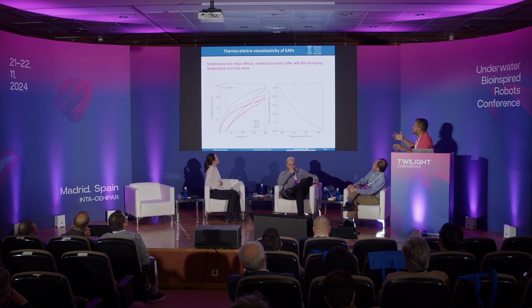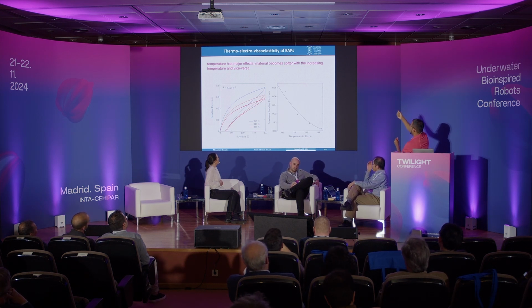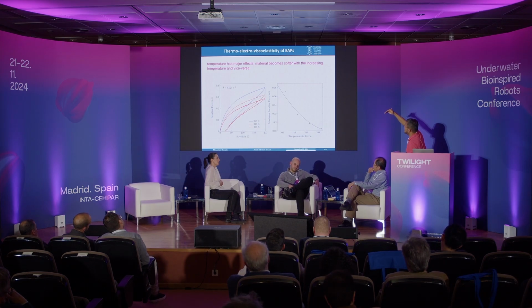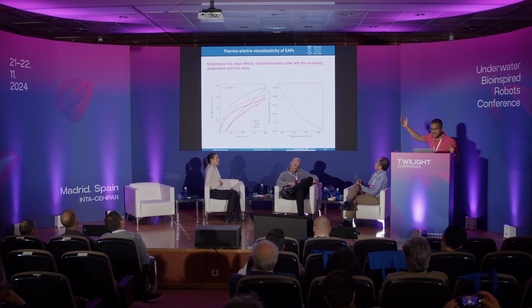Then what will happen if you do an electromechanical test, right? Electromechanical test means you are pulling the sample, and at the same time you are applying the electric voltage. Since you are applying the electric voltage along the thickness direction, the polymer will expand in this direction. So in the same direction you are applying the mechanical field. That means you are getting a lesser response compared to the mechanical case. So this is the case.